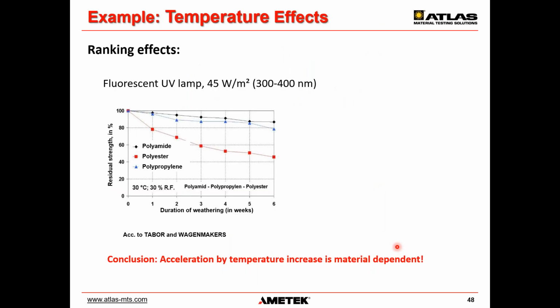Not all rank reversals are the result of poor sunlight simulation, as discussed in the last paragraph. The reaction rate of photochemical degradation processes depends on a number of different factors, including effective irradiance and temperature, and the particular material sensitivity to the irradiance and temperature. And finally, the property change.